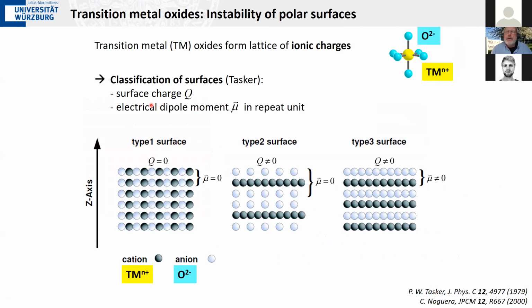If you have a material that is composed of ions, you have to think very carefully about the distribution of the charges in this ionic compound when you terminate a crystal, when you create a surface. And you can classify the surfaces in different categories. You can have an electrically neutral surface, so the charges of all the ions add up to 0, and where you have no dipole moment at the surface. You have surfaces where the surface is charged. For example, here you have all the negatively charged ions on the first layer, and then the positive ones on the next one. But you don't have an overall dipole moment.